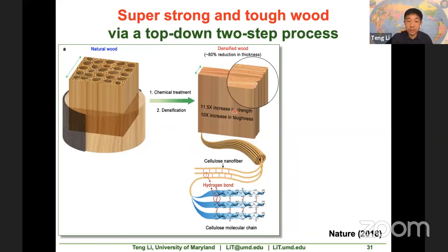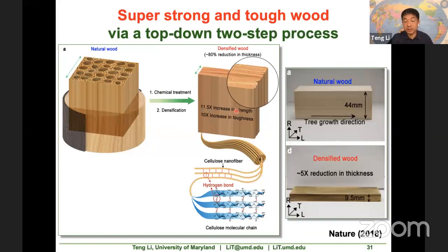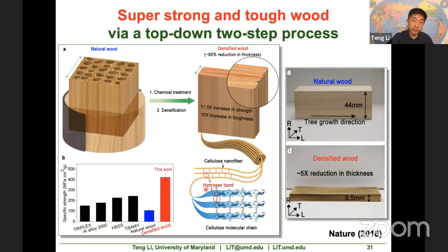We can show that you can significantly reduce the thickness of the wood by 80%. So this is a natural block of wood with a thickness of 44 millimeters. After densification, it is only 9.5 millimeters. And we maintain the alignment of the nanocellulose fibers in the natural wood. Indeed, this further densification makes this alignment even better. Let's see the performance of this material.